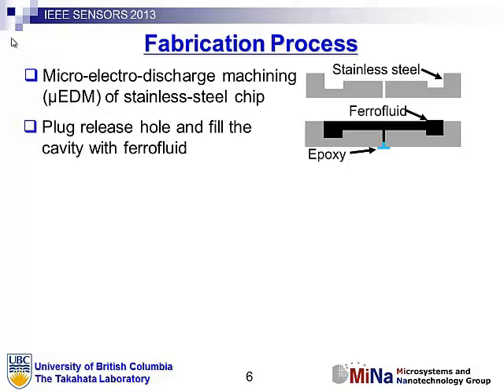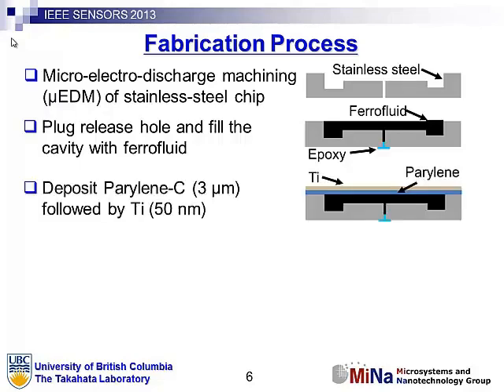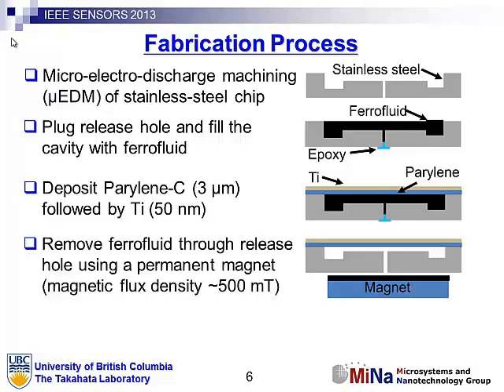Then there was depositing of ferrofluid inside the cavity that allowed for deposition of the membrane over top. The chemical vapor deposition of the Parylene, followed by the E-beam deposition of titanium. Then the epoxy was removed from the bottom, and a permanent magnet was used to essentially draw out almost all of the ferrofluid.